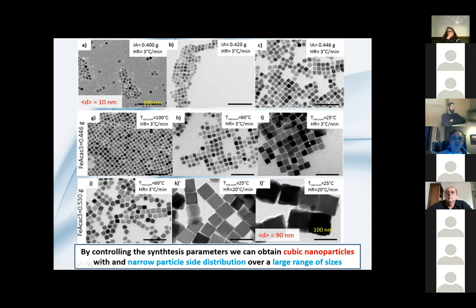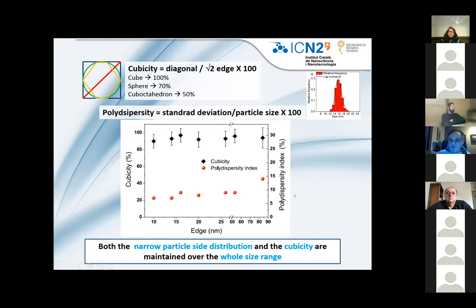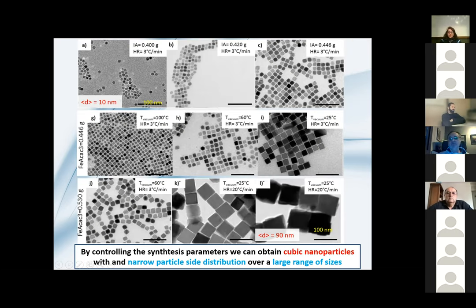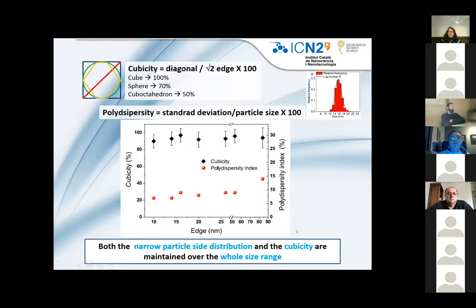And another approach we took was to play with the heating rate and the total amount of sample. You see that by controlling the synthesis parameters, we can get cubic particles with a very narrow size distribution over large particle sizes, ranging from 10 nanometers to 90 nanometers.